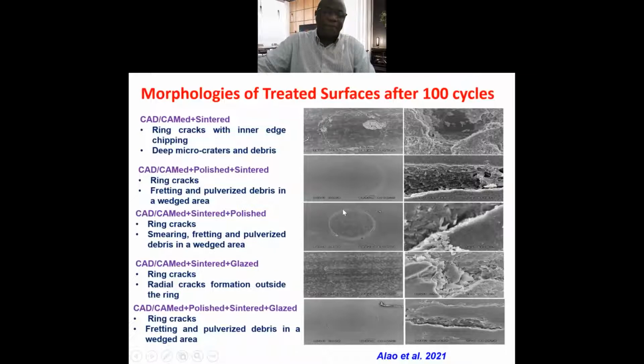CAD-CAM sintered and polished, you can see the ring cracks, smearing and fretting, and then pulverized debris in the wedged area. For the CAD-CAM sintered glaze, you can see the ring cracks, then further loading leads to radial cracks formation outside the ring. You can see the formation of the radial crack. This is the radial crack forming outside the ring crack.